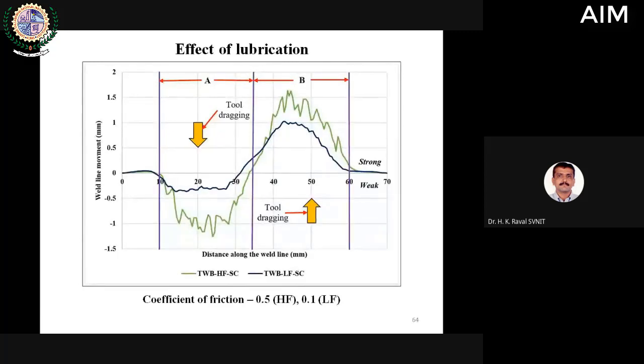This is the study extended for the lubrication effect. We did try with two different lubrications. One is with low friction. This is a simulation study only, so there is no actual lubrication used. We tried different coefficients of friction: 0.1 and 0.5. 0.1 is the low friction, 0.5 is the high friction. And one can notice here that because of the lower friction, the tool dragging effect is less. Because of higher friction, which is shown with the green color, the tool dragging effect is more, and that gives rise to a differential weld line shift. So to control a weld line shift, one should also control the coefficient of friction. So that is the outcome of this particular finding.